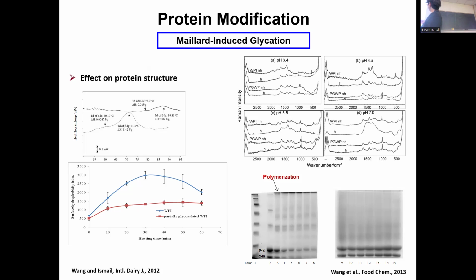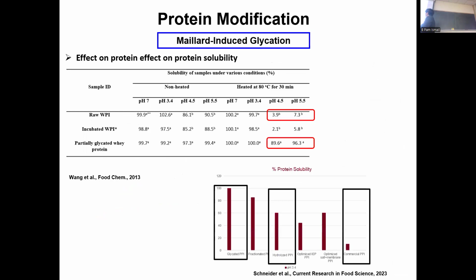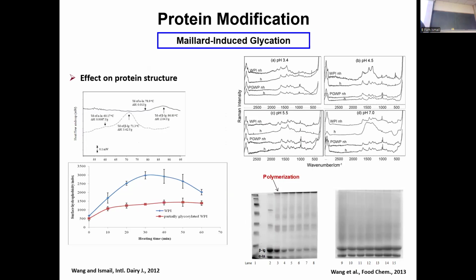We looked at the structure using Raman spectroscopy, and the glycated protein did not change in structure. We had very good rigidity, so it didn't denature with heat. Whereas the whey protein denatured and changed in the spectra at different pHs, the glycated whey protein stayed very rigid in structure. May not cause an increase in the polymerization? No. Glycation reduced the polymerization because of steric hindrance. Again, we made sure it's at the initial stage only. It didn't go to the advanced stage where you produce big polymer.